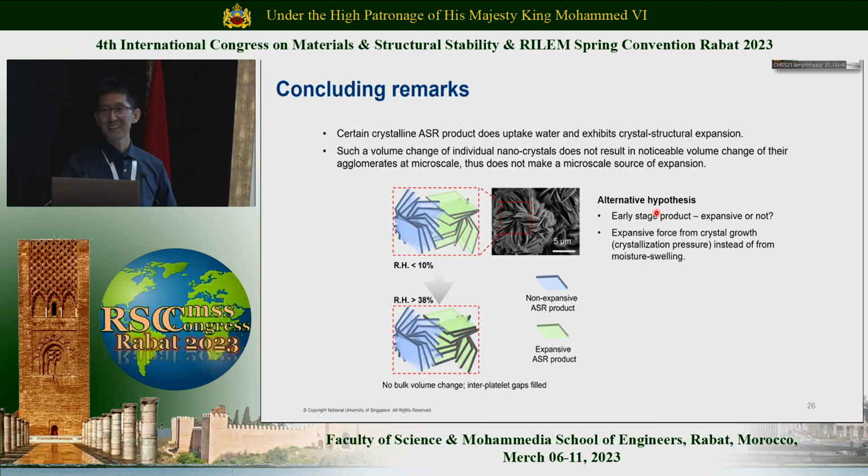And it's again a challenge to the textbook idea that the water absorption leads to the swelling and expansion cracking of the ASR. We are finding something that contradicts that. So we went to alternative hypotheses. For example, this cracking may not be due to this crystalline product.